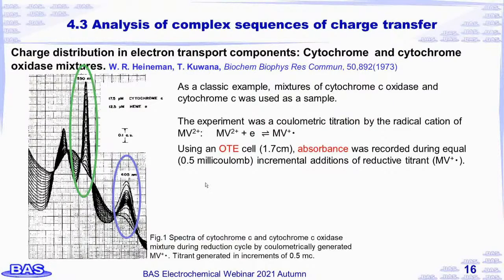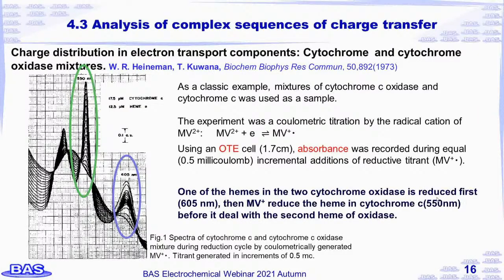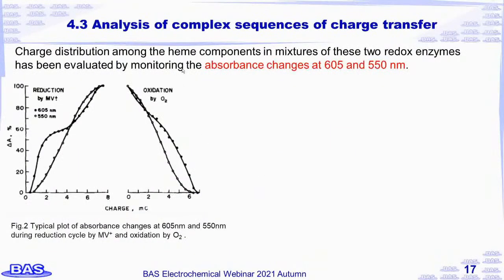It means one of the hemes in the cytochrome oxidase is reduced first. Then the monovalent cation of methylviologen reduces the heme in cytochrome c before it deals with the second heme of the oxidase. Charge distribution among the heme components in mixtures of these two redox enzymes was evaluated by monitoring the absorbance changes at 605 and 550 nanometers. In Figure 2, the left figure shows the absorbance changes at 605 and 550 nanometers during the reduction cycle by the monovalent cation of methylviologen. The right figure shows the absorbance changes during oxidation by O2.